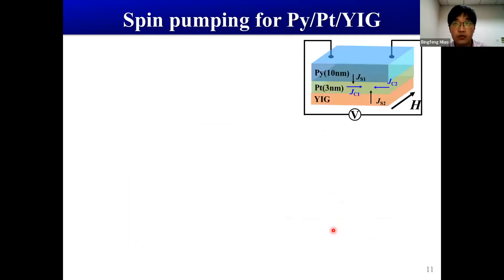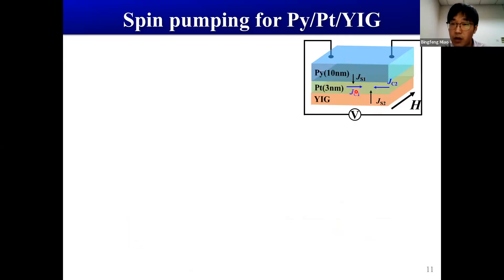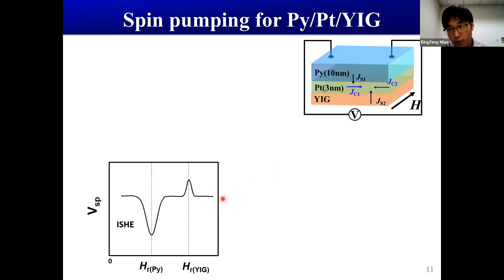We now present our results. Suppose we have a permalloy/platinum/YIG trilayer. When YIG precesses, it injects spin current from down to up; when permalloy precesses, it injects spin current from up to down. Due to the inverse spin Hall effect, these two opposite spin currents result in opposite charge currents. Since the ferromagnetic resonance fields for permalloy and YIG are different, we would expect to observe a peak-to-dip feature. In our experiment, we place the stripe onto the coplanar waveguide and feed it with a microwave source generator, modulating the microwave on and off to increase the signal-to-noise ratio, detecting the voltage along the stripe at the same frequency using a lock-in amplifier.